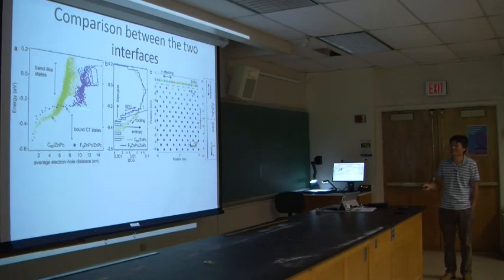Now we can count the number of dots in each of these energy intervals, and we get this kind of density of state function, right? Of course we can also look at the spatial distribution of the electron and hole for each of these individual states too. So I pulled two examples here for these two different interfaces, right? The idea here is these states usually have a lower density of state for the tightly bound states, because you really don't have much possibility to have these bound states, right? You need to have the electron and hole right at the interface. When they start to delocalize, automatically they are farther away from the interface and have weaker binding.